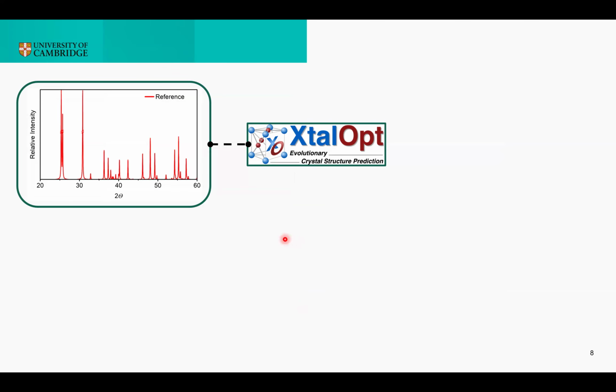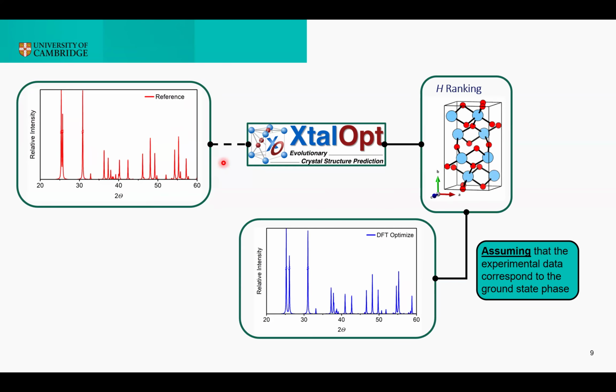Therefore, oftentimes we are asked by experimental collaborators to perform a crystal structure prediction to help the characterization of new compounds for which the powder diffraction was collected, but that was still particularly challenging to solve due to this problem. So theoretical calculations in this case should support experimentalists for such identifications. The standard procedure was to run a crystal structure prediction to check the powder diffractions of the most stable phases, and making this comparison between the theoretical and the experimental powder diffraction. And if we were lucky, we would associate a theoretical structure to the experimental data. This method, however, was very inefficient, and it was easy to miss good structures, especially if they were not the thermodynamically most stable at a given level of theory.